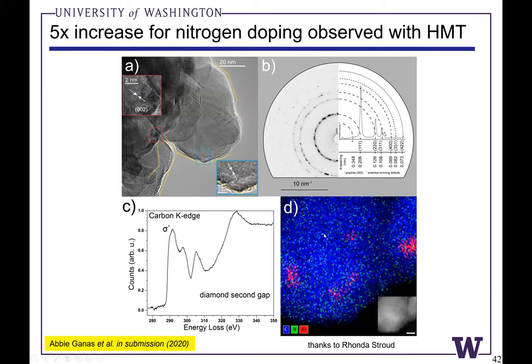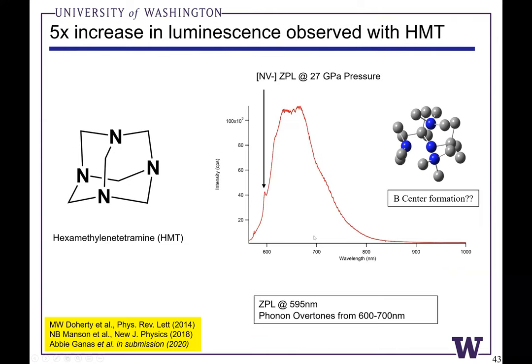But very excitingly, Abby, these little green dots in the image, if you can see this, if it shows up okay through Zoom, these little green dots are nitrogen X-ray photons that get emitted in Rhonda's microscope when the electron comes in and kicks out a 1s electron from the nitrogen, and X-ray fluorescence can be used to map out the nitrogen distribution in these materials. And Abby has shown a fivefold increase in nitrogen in the nitrogen-doped materials versus the non-nitrogen-doped materials.